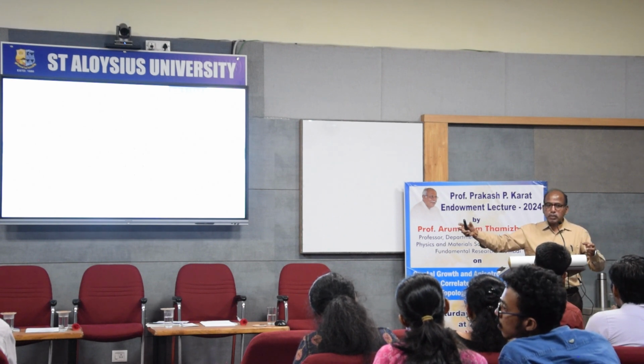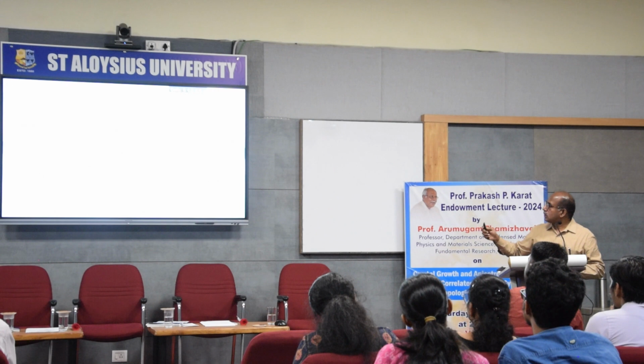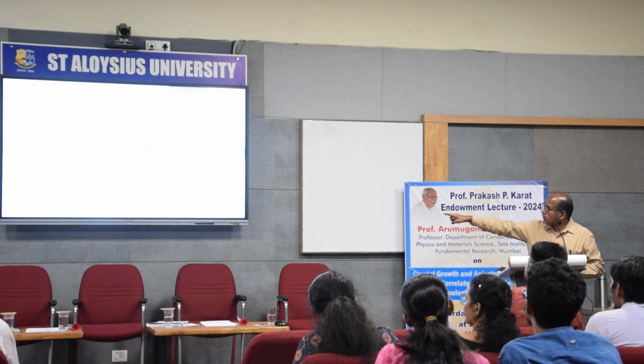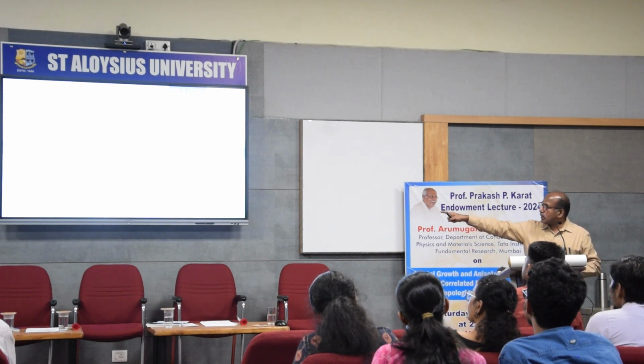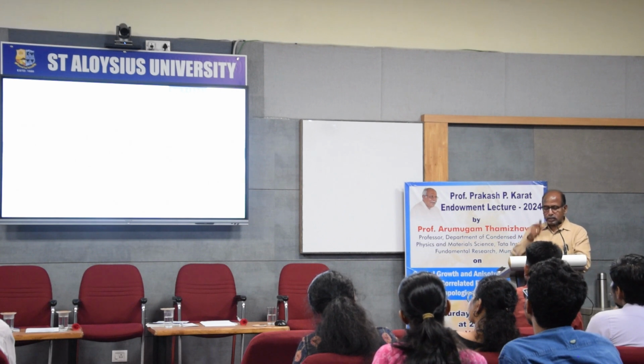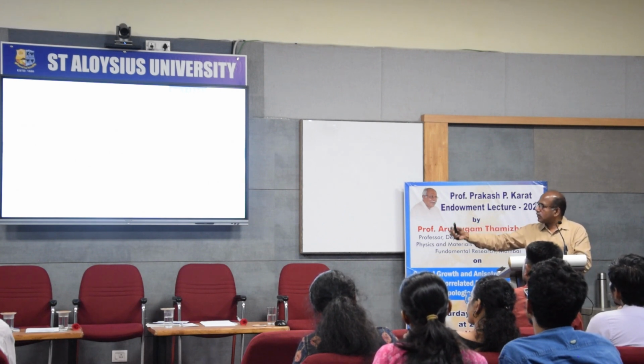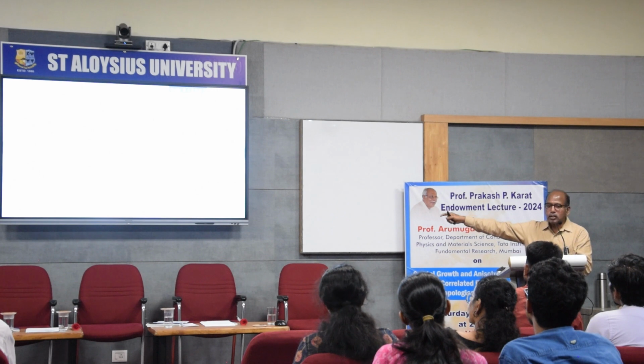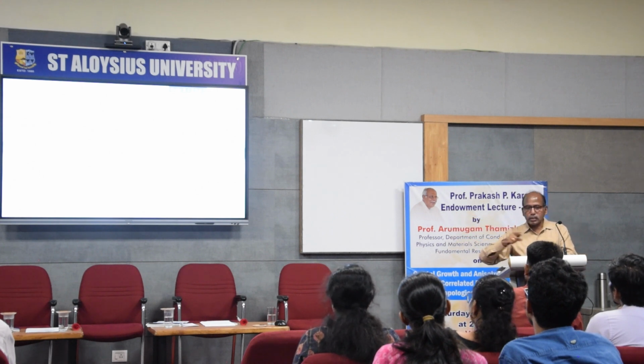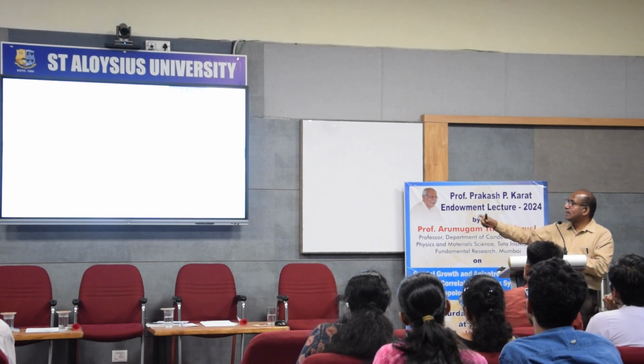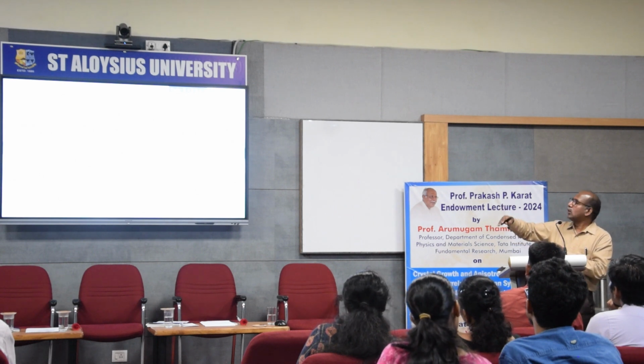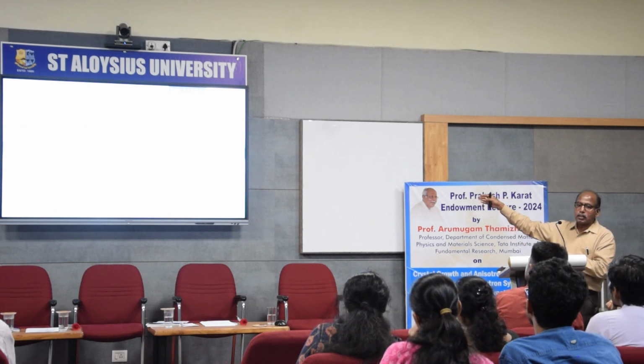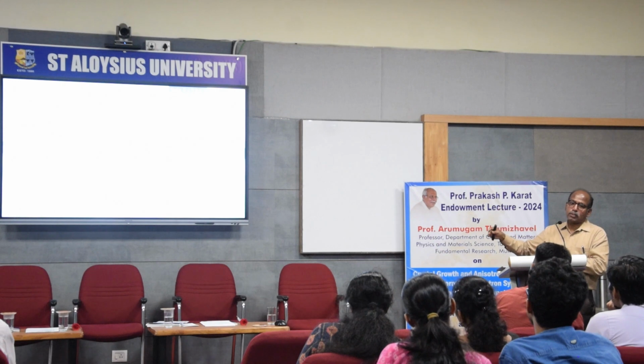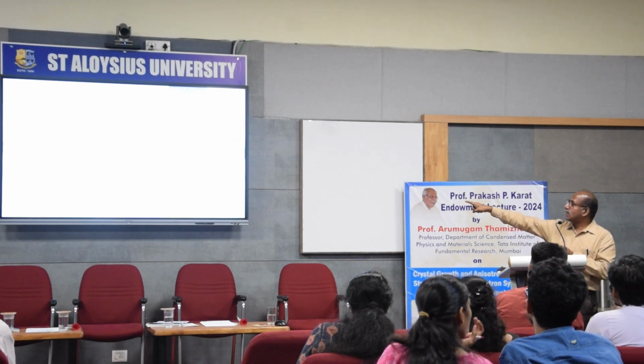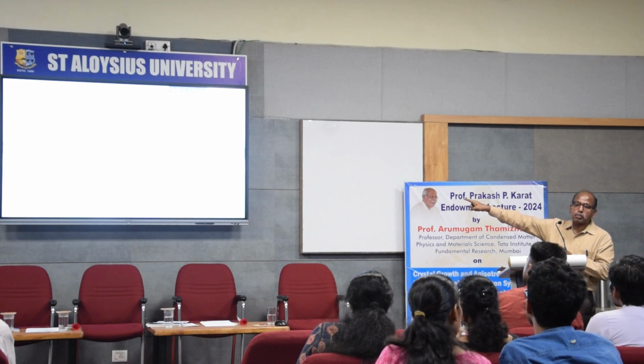So in this effect, the conduction electron screens the F electron. Maybe the distance is much smaller, or much larger. See, the bottom curve, that is at 0, means the F electron site, and as we increase the distance, the next F electron is as a function of R. So there is one F electron, and the other F electron is a function of R. Depending on the distance, you have this oscillatory behavior. So you can have either ferromagnetic or antiferromagnetic, ferromagnetic or antiferromagnetic. Everything depends on that J, which is the exchange interaction.